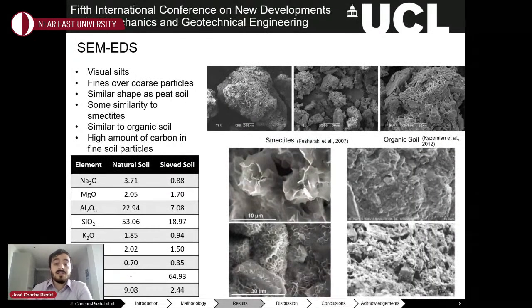The SEM images are shown in the top right picture. It can be seen that the quartz grains are covered with small clusters of particles. These are the quartz grains. Those clusters have both angular silts and web-shaped particles. If we take a look at the microscopics from smectites, for example, these ones, it can be seen that there is not too much resemblance with the studied soil, whereas there is much more resemblance with an organic peat soil reported by Kazemian.